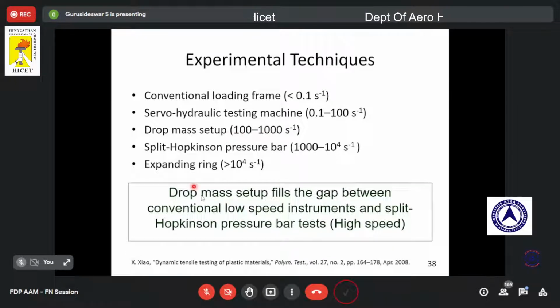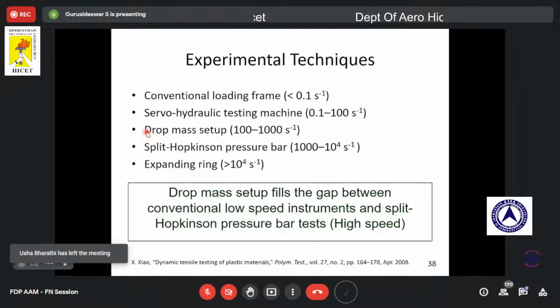And also we have found there is a gap in the literature. People have focused on low temperature, low strain rate, and people have focused on high strain rate. But we could not find enough literature on this intermediate strain rate, that is from 100 to 1000 per second. So that is why we have made an attempt to do the testing in this region. For that, we have employed a drop mass setup that was indigenously designed and fabricated at IIT Madras. So today I'm going to share my results from experiments on this drop mass setup.